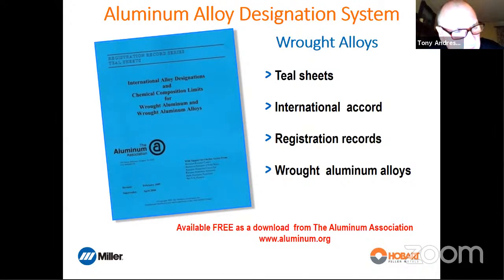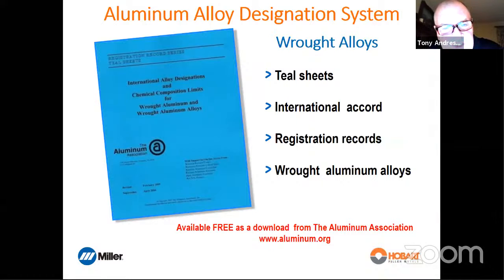There are, I can't remember the latest number, probably about 600 or 700 different aluminum alloys listed in the teal sheets. And every one of them has its chemical composition. So you will realize just now when we talk about cracking, if you don't understand the chemical composition of the alloy you're welding, it's the blind leading the blind. You can't determine how to weld it. You can't even determine whether it's weldable, because there are some aluminum alloys out there that cannot be welded without cracking. And it's because of the chemistry.